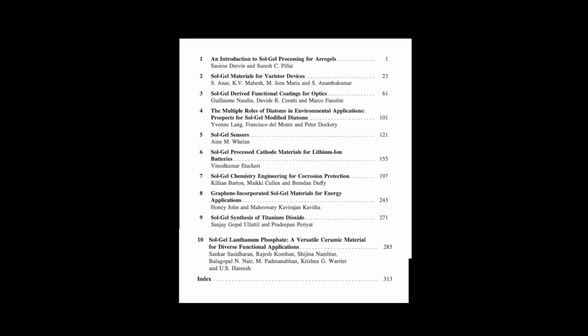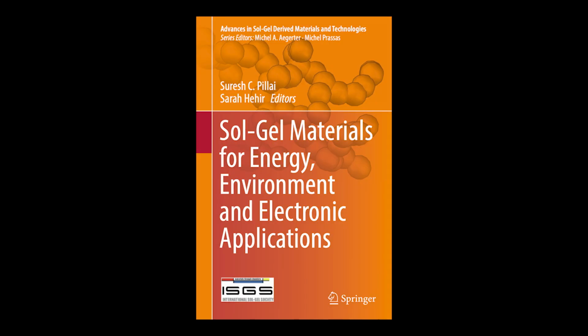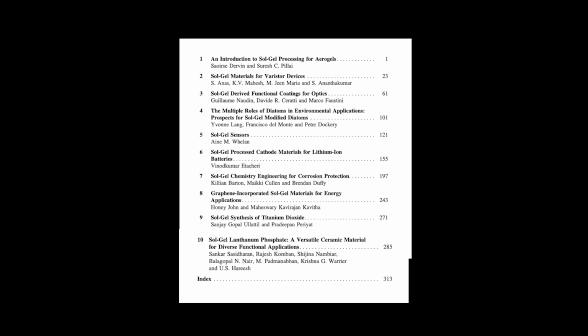Amazing. And this array approach works for detecting ions in solution, too. Yes, absolutely. Sol-gel techniques allow for the grafting of highly selective receptor molecules onto the surface of mesoporous silica, which has a huge internal surface area. For detecting toxic mercury ions, Hg2+, in water, for instance, researchers grafted specific receptor molecules onto the silica surface. The resulting material selectively changes color from yellow to red only when Hg2+ ions are present, illustrating really high precision and selectivity thanks to that tailored surface chemistry enabled by the sol-gel route. The chapter also notes a highly specific fluorescent sensor for nitrite, NO2-, in natural waters, built on similar principles.